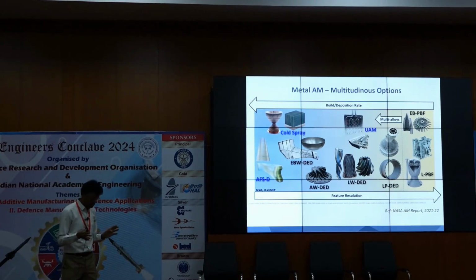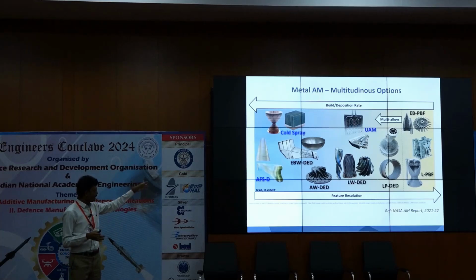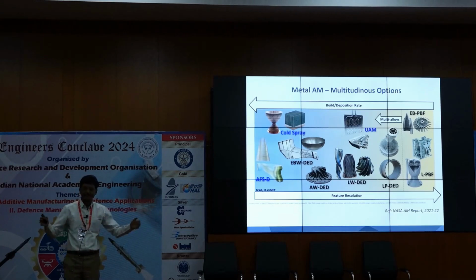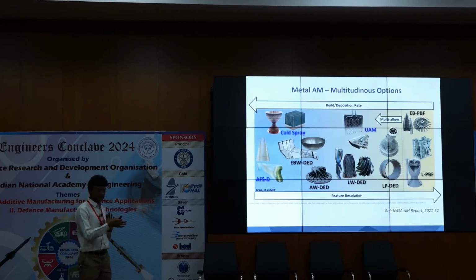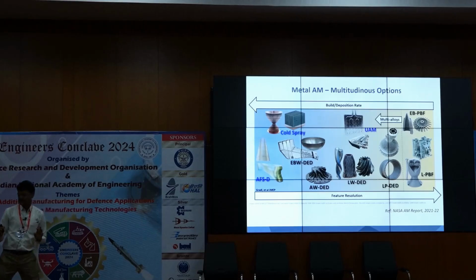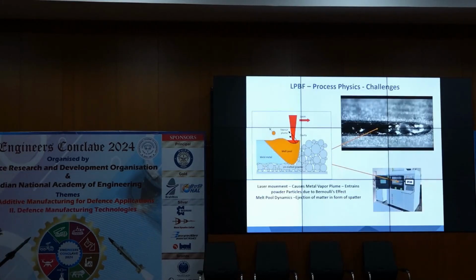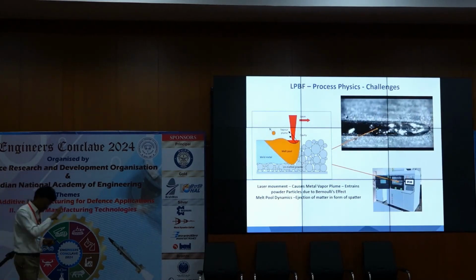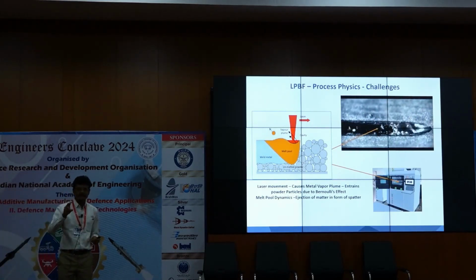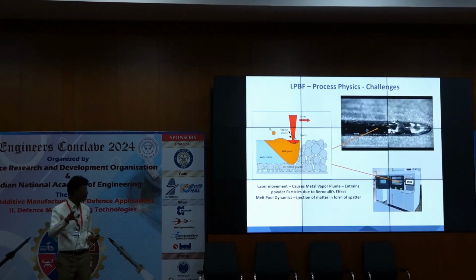So if you were to talk about high volume or high deposition rates, definitely you will have proclivity towards the DED techniques where you can make large parts in limited time. But if you are talking about high resolution parts, we need to think about technologies like laser powder bed fusion. And central to this particular process is the interaction between the energy source and the metal powder. And continuously, there is the melting and solidification which is happening under the influence of high thermal gradients.